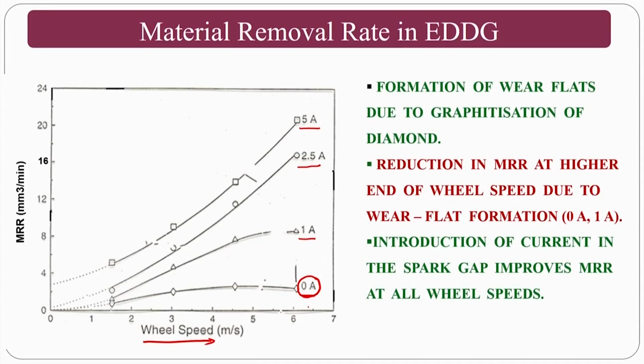Since there is no sparking, there is no melting and evaporation, because of which the workpiece's original hardness plays a major role, and you cannot remove much material. You may observe very fast glazing, because normally this EDDG application is for harder materials, and the diamond particles are also hard, and your metallic bonding will also be a hard grade. Okay, it is not soft. In those circumstances, you may experience glazing, that means your abrasive particles go off. Okay. So you should be very careful, that is why the material removal is less.